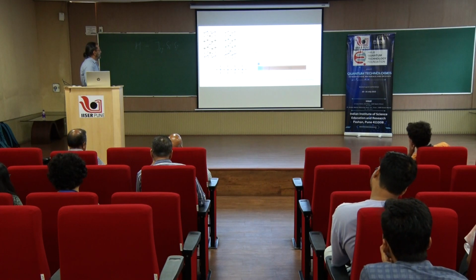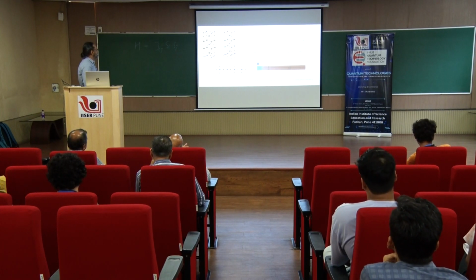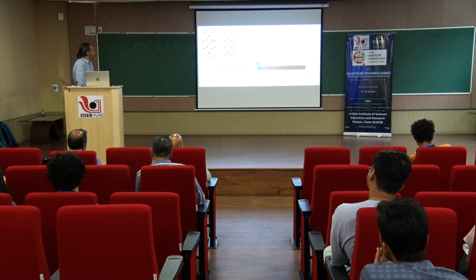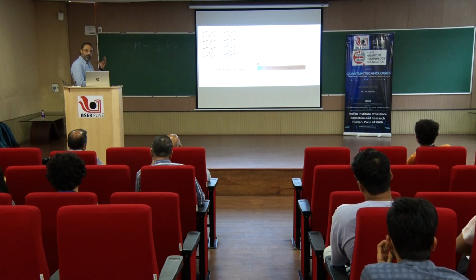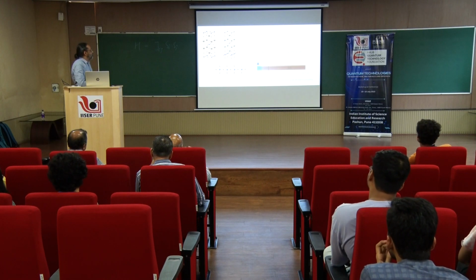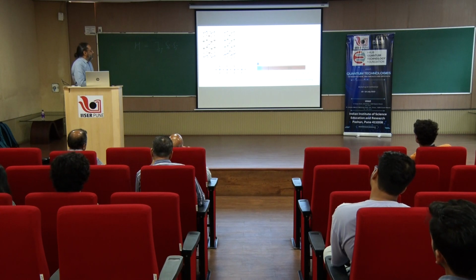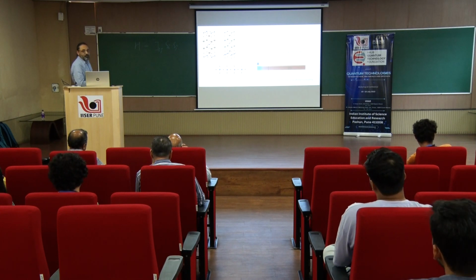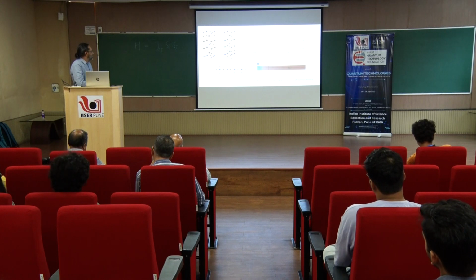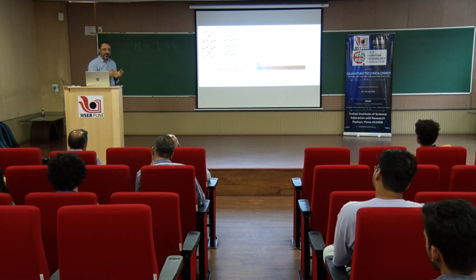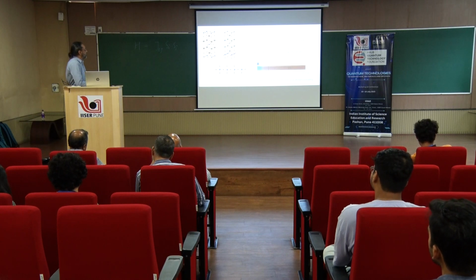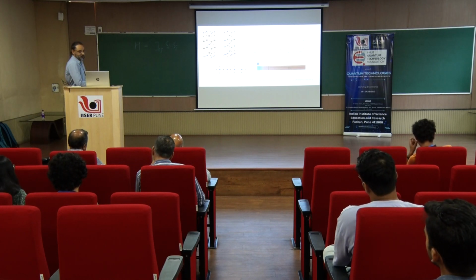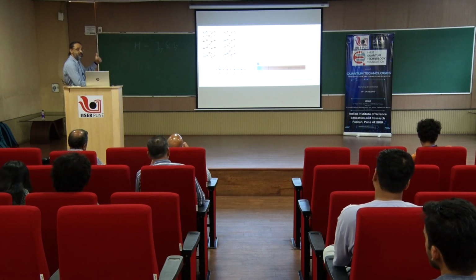Now, in the 1D chain, like for instance this one, I said that there is no interaction between these two coppers, but is it really true? Yes, you have removed the intervening oxygen. So, super exchange is gone, right, but they can still have a very feeble dipolar interaction between them. Besides that, this copper can interact with this copper. The exchange path is quite long. For instance, the exchange path in this case is via this oxygen and then this strontium and then this oxygen and then this copper. A longish exchange path, but the exchange path is there. So, therefore, the copper spins are interacting primarily along this direction. That is the in-chain interaction.